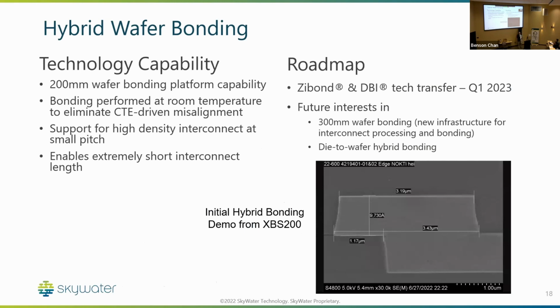So that technology is being implemented at a 200 millimeter wafer bonding platform capability right now. You've seen before that this is a room temperature bonding process, so it really does improve things like alignment and CTE driven problems that you get from other packaging approaches. It does support high density interconnect at small pitch. The XBS200 system is rated to 100 nanometers of alignment tolerance. So there's a lot of capacity and capability in that platform.